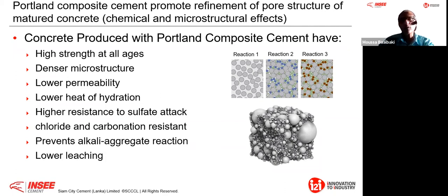For me, I'm more concerned with leaching for reinforced concrete. Not only the carbonation, but the leaching for the reinforced concrete is what? I have a water reservoir. I have a certain porosity. I have a lot of Portlandite. If the water permeability is a little bit high, I can leach out the Portlandite. So by leaching out the Portlandite, I reduce the pH. Therefore, I have what we call a decalcification. And if the pH now reaches 9, the reinforcement is depassivated.